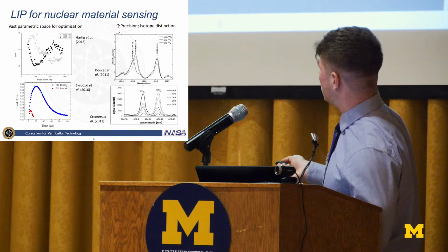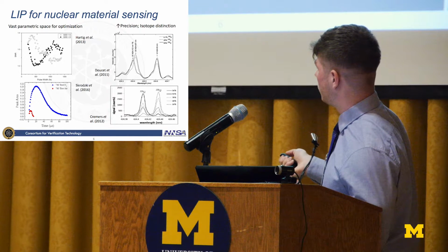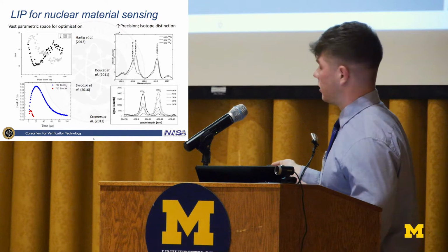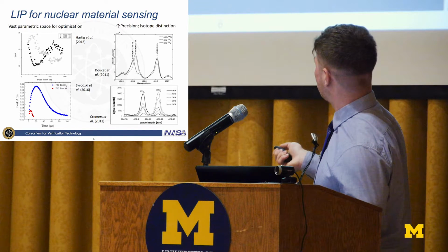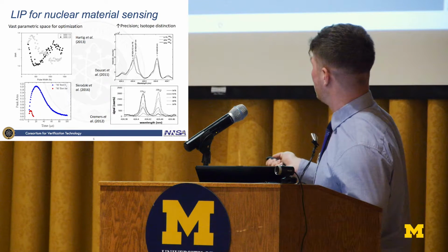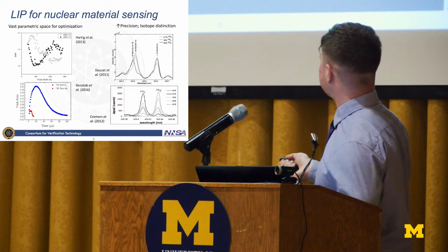Some of my previous work, looking at a uranium line with an absorption measurement, just varying the ambient gas surrounding the target between air in the red and nitrogen in the blue, signal increases almost 5 times.